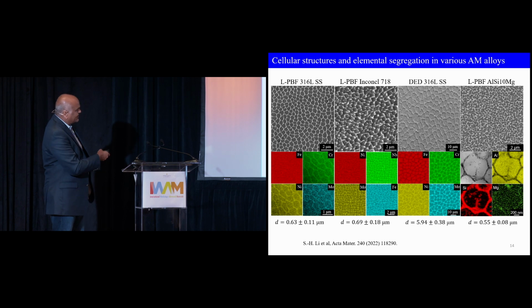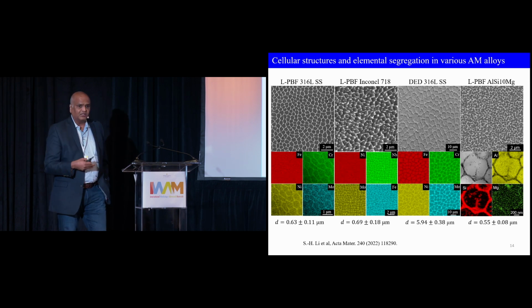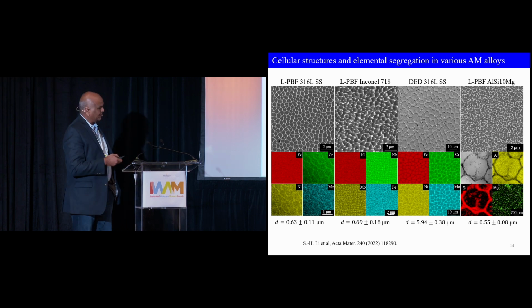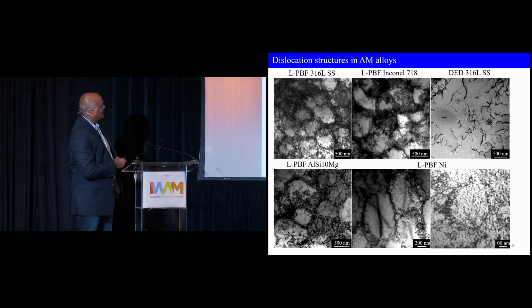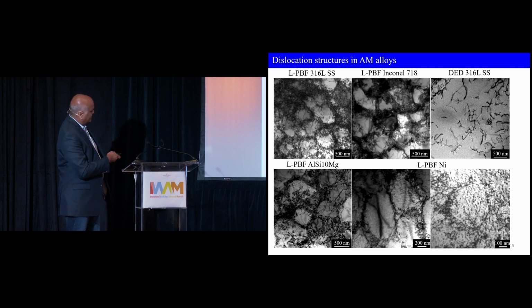There is elemental segregation, as these maps show, to the cell boundaries - solutes segregate to the boundaries. And if you zoom in and look at it in a microscope, you will see a very large dislocation density decorating these cell boundaries.